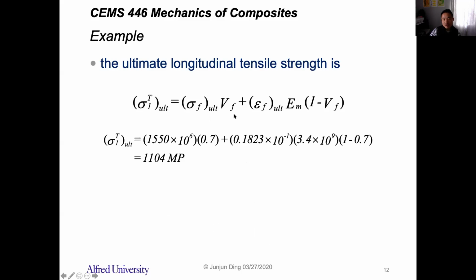So that's the ultimate strain of the composite. You use the ultimate strain of the composite to calculate the ultimate tensile strength. The ultimate tensile strength will be equal to the ultimate stress of the fiber, because the fiber will fail first, right? Times the volume fraction of the fiber, plus the stress applied to the matrix at that time, which has to be calculated based on the strain applied to the matrix, right? Because the strains are the same. You use the strain and the Young's modulus of the matrix, and that's the stress applied to the matrix. So in this way, you can calculate the ultimate longitudinal tensile strength.